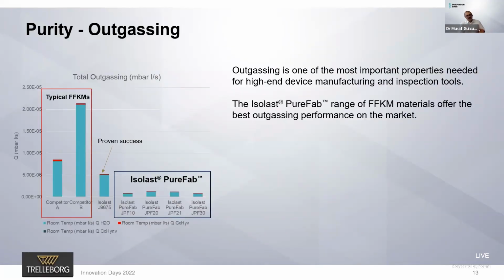So now let's talk about outgassing. Outgassing is another important property which is mainly needed for high-end deposition applications in semiconductors, such as ALD, PEALD, or PECVD kind of applications, thin film deposition methods. So outgassing is extremely important because we are talking about 2-3 nanometers. In the near future, those will be commercially available, and even a small molecule released from an O-ring or any component of the chamber can really have a bad effect on the yield.